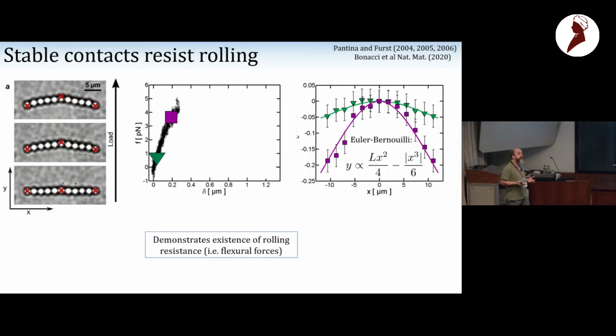The fact that it's bending tells you that the contact resists rolling. If the contacts were rolling, like if you take a string and do that, you would see a triangle. If you see a rod-like shape, it means that all the contacts are resisting rolling. So that was something that Pantina showed. And so our idea was that maybe this flexural stiffness might depend on time. So the picture is that we rapidly gel, but we have a system where the properties of contact will vary with time.